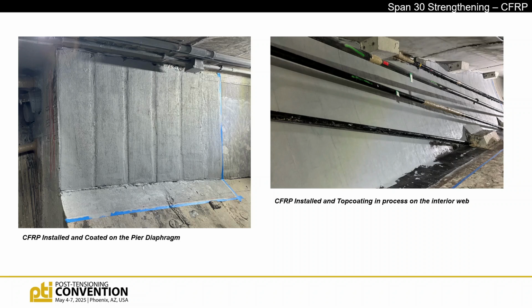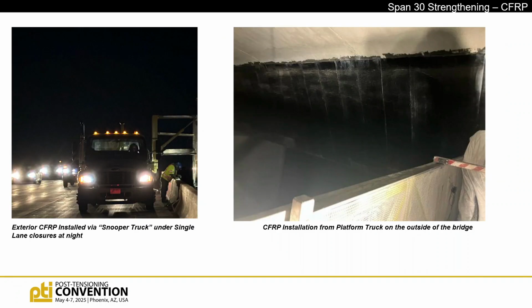So we chose to do the inside first, mostly because there was record rainfall in South Carolina at the time, and they hadn't had a dry week in I think 3 months, and then we were able to get outside immediately after that. Under lane closures, we could only close one lane down, so we got in on snooper trucks and access platforms, installing everything on the outside. We managed to hit the 1 week when we did this externally where it stayed dry all week, right before the temperatures dropped. So we were very fortunate in the timing of everything. There's a lot of logistics that go into that.